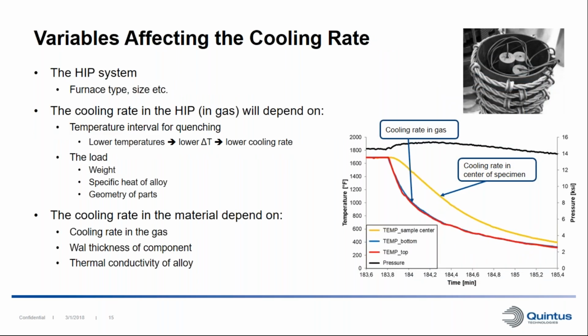If we look at variables that will affect the cooling rate in the HIP system, we have, of course, the HIP system itself. The furnace type and the size of it will determine your cooling rate, but there are also other variables. So for a given HIP system, the cooling rate in the gas will depend on, first, the temperature interval that we're looking at for quenching. So, for example, at lower temperature, if we're HIPping aluminum, we have a lower delta T, and that will give us a lower cooling rate.